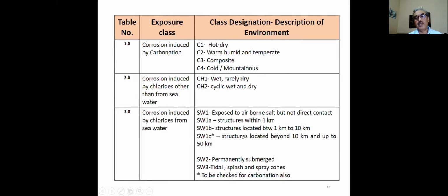Now 10 to 50 kilometers is mentioned here, but generally chloride will not be critical in this zone. So we have put a note that these structures should be checked for carbonation also, and chloride also you have to check, because the chloride values are low in this case, which are to be considered. Those values have been given in the code.